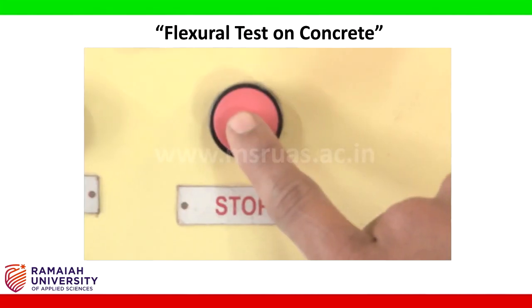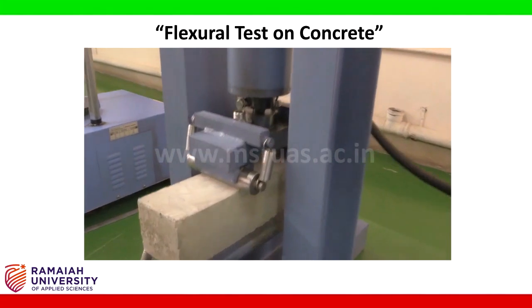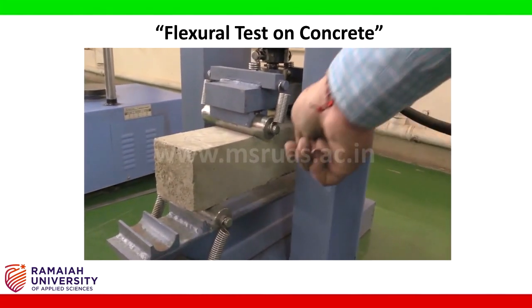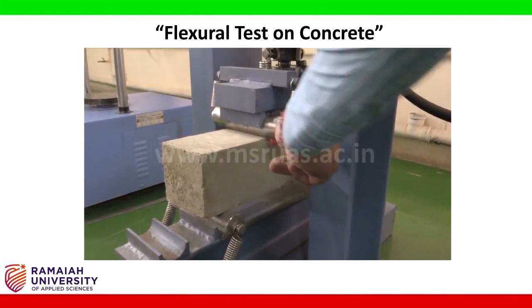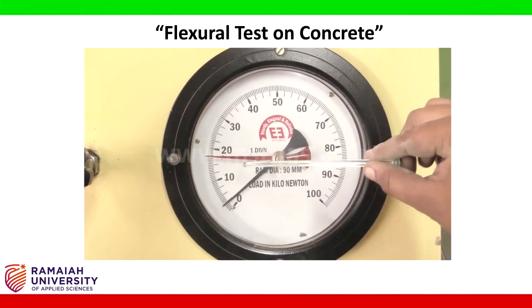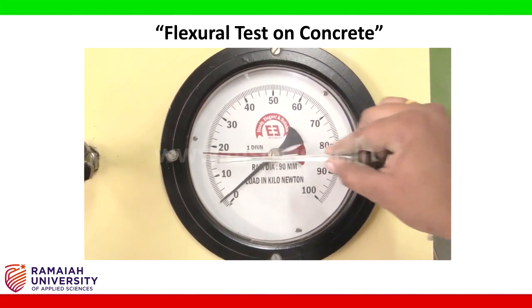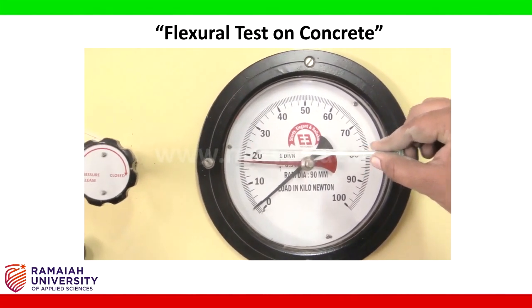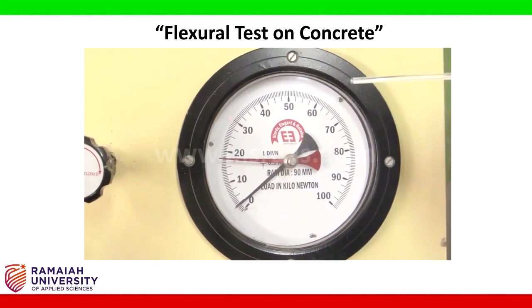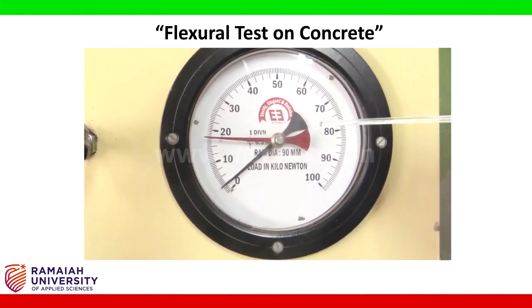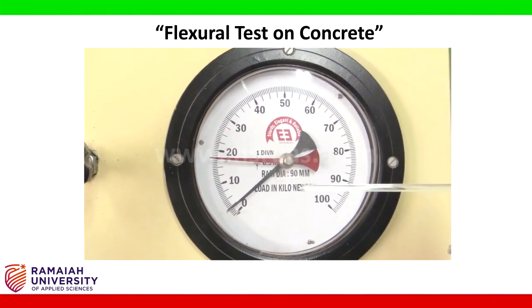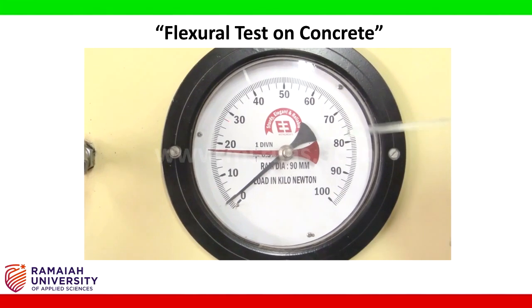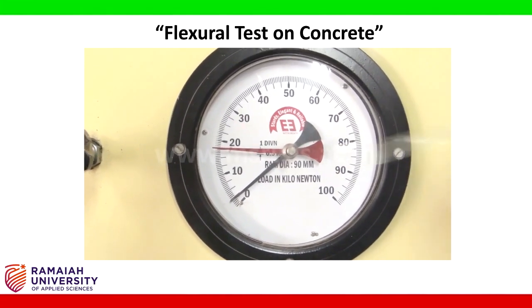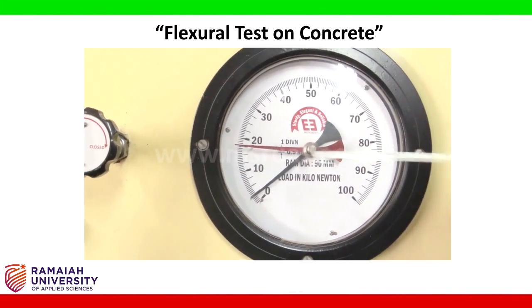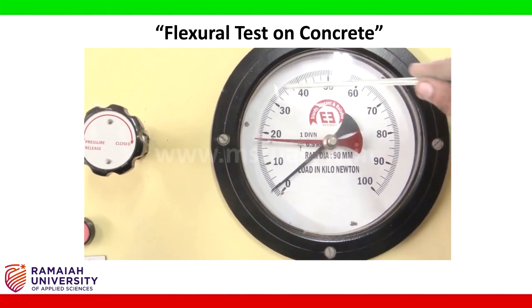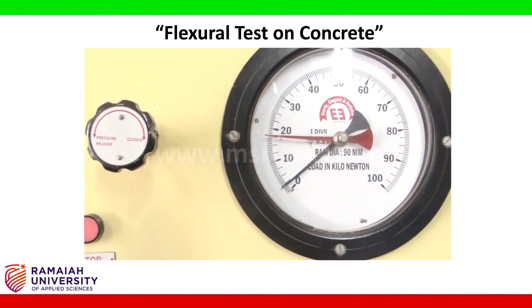So you observe, you stop the machine and note down. You observe at the center there will be a formation of crack. At the end there will be the formation of crack. Note down the value of reading on the dial gauge. This is what we call as P. Okay, use of formula, FCR is given by PL by BD square. So when to use the formula is, if your crack is between 1/3 to 2/3, we are going to take up the effective length. If the crack is at the supports, that is within 1/3 or more than 2/3, we are going to take up the total length. Let us observe where the crack is. But at this particular point, what we are going to do is, we just note down P value, that is the load of failure.